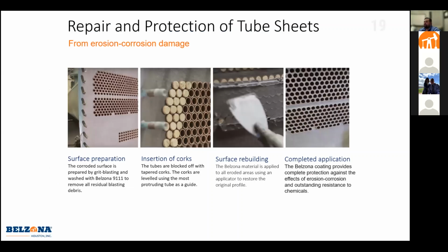This is just a little before, during, and after. This is a chiller we've done in a plant, tube sheet. We corked it and blasted inside down to an SP10 profile. And what we do, we cork the tubes for 2 reasons. Cork them during blast to stop any damage from getting in the tubes and to stop any sediment or blast media, etc., from getting in the tubes. Then we recork and get them flush with newer corks. And that helps us for when we build up our paste grade.